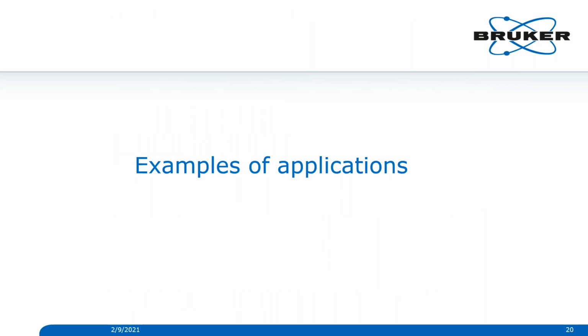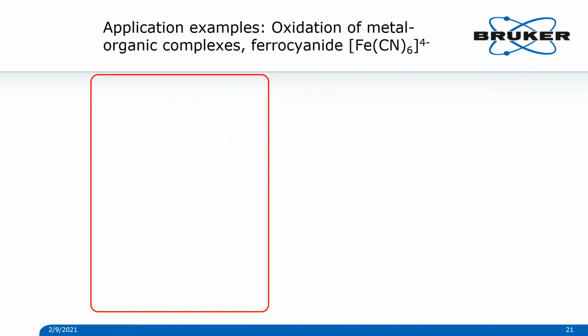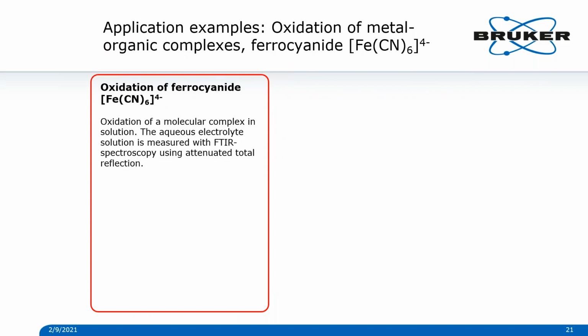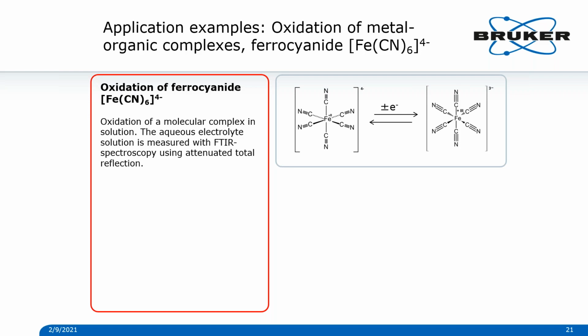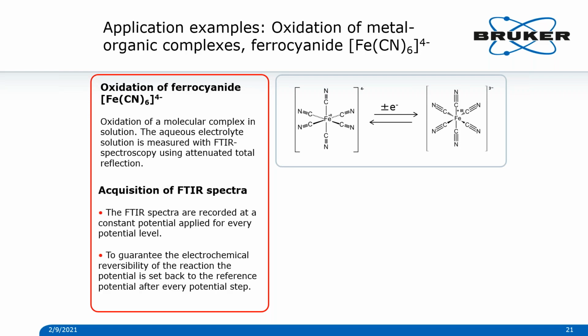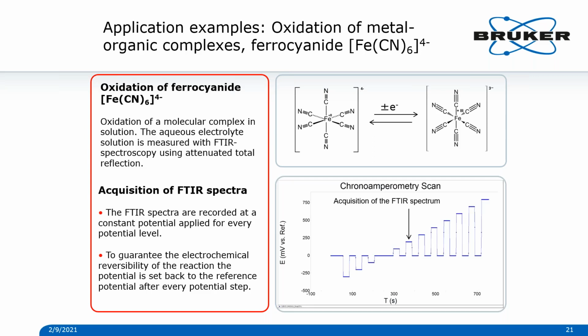So now I switch to a few examples of such applications. The first one is the oxidation of metal-organic complexes of ferrocyanide. We use FTIR spectrometry in reflection mode. FTIR spectra are recorded at constant potential applied at every potential level. And to guarantee chemical reversibility of the reaction, the potential is set back to the reference potential after each step. The example on the right shows how we change potential and record the signal at each step.